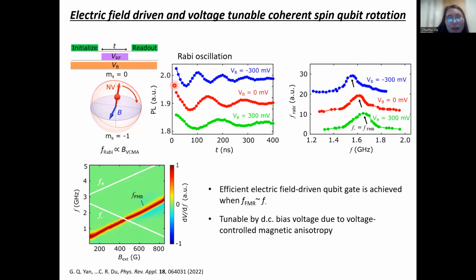So we indeed observe a very clear Rabi oscillation of the NV center as a function of the duration of the radio frequency voltage applied across the junction. So this suggests that indeed the NV center coherently rotates between two quantum states induced by the electric field in the hybrid device. And we also find the Rabi oscillation can be tuned by applying a bias voltage across the junction. This is because the bias voltage controls the magnetic anisotropy. So this changes the ferromagnetic resonance frequency of the device, which controls where it crosses with the NV center. So this enables electrical control of the coupling between the NV center and the spintronic devices.